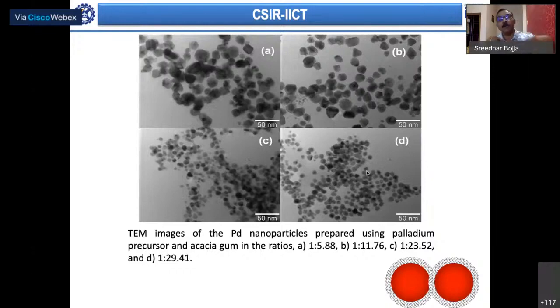This is one point in the stabilizer discussion, where we talked about the controlled growth of the particles. By changing the concentration of gum, you can tune the reaction parameters so that you can have particles of uniform size or shape, and also minimize the size by having appropriate concentration. So at higher concentrations, due to the hindrance on growth, the particles are limited to a smaller size, and you can play with such kind of thing.